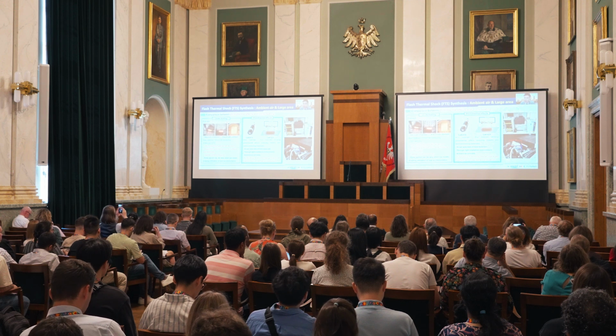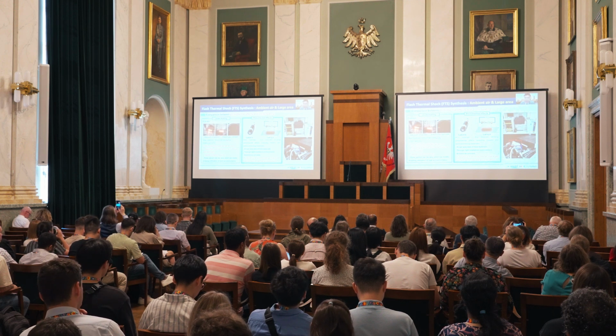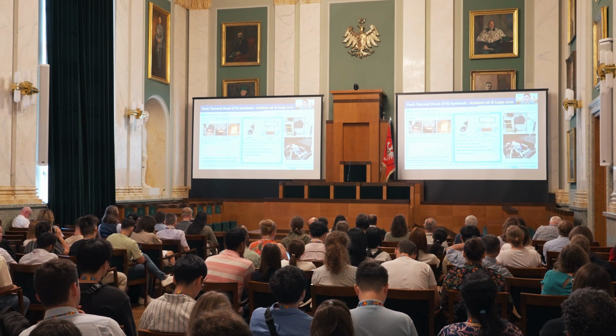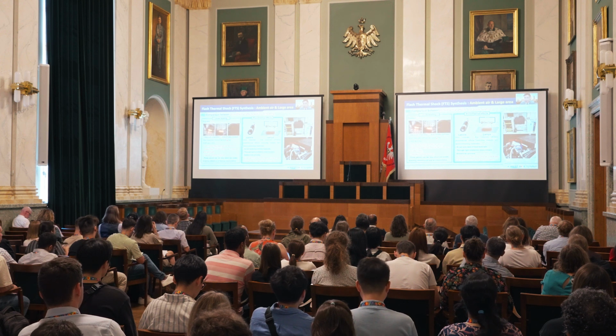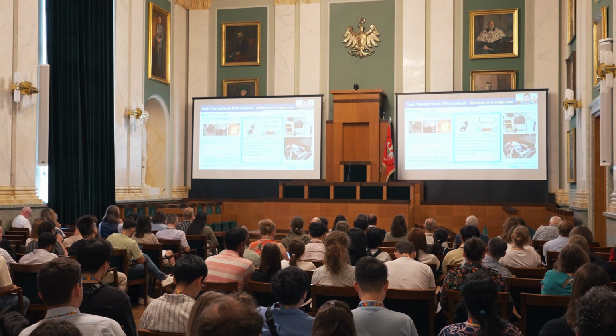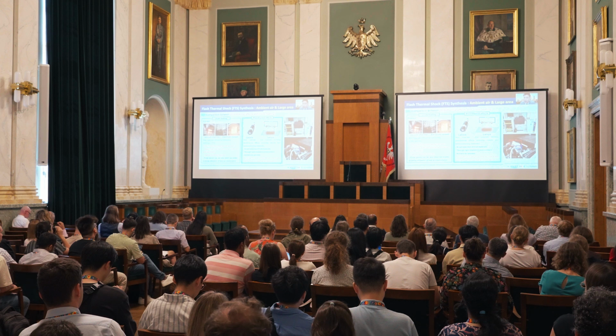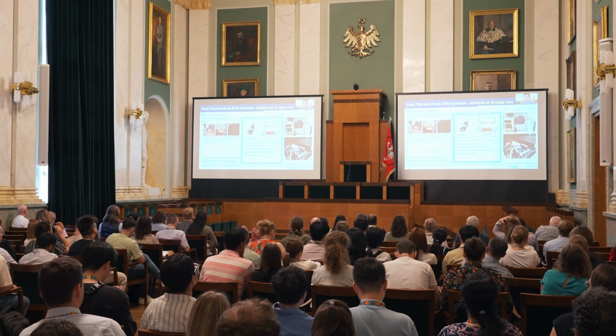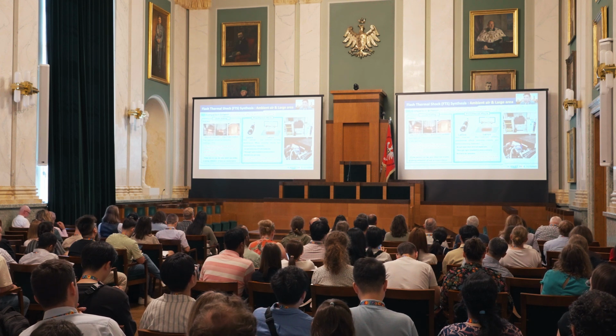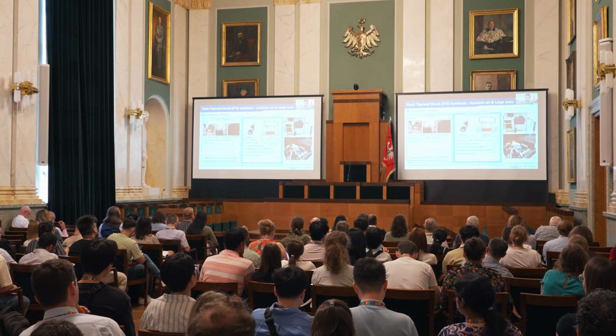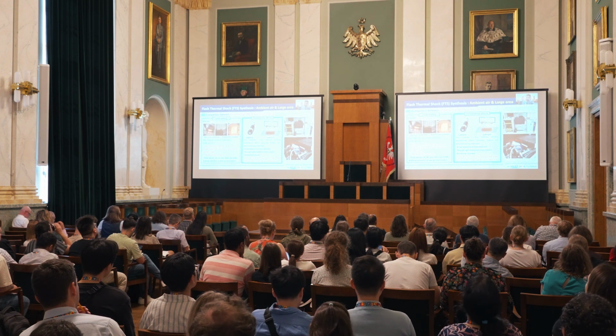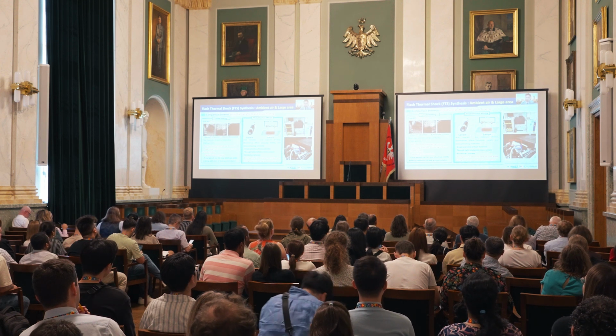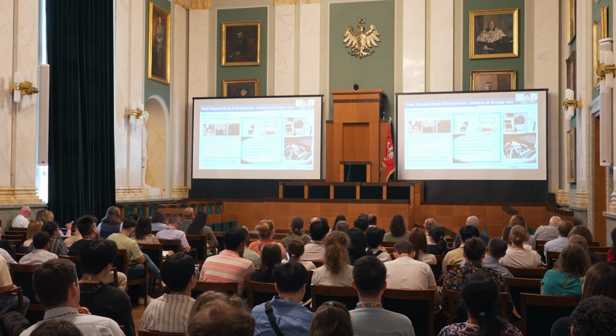So I like this Joule heating. Yes, this is a very powerful approach for millisecond level high-entropy alloy and single-atom catalyst design. But as I mentioned, we always need the carbon material. With this photothermal effect, without carbon material, we can use this IPL process because, as I told you, this is a remote, just a light irradiation approach.